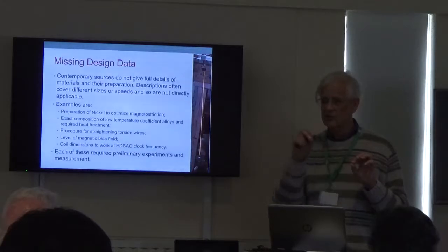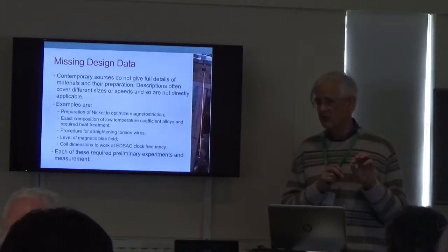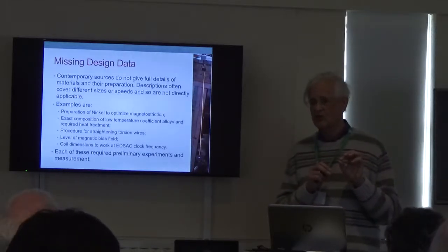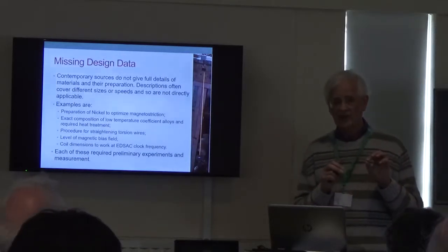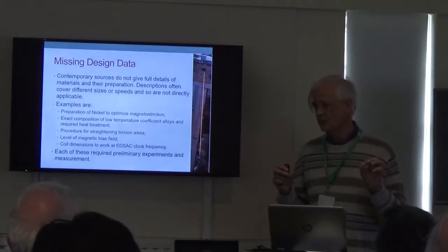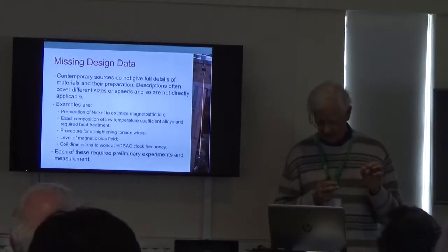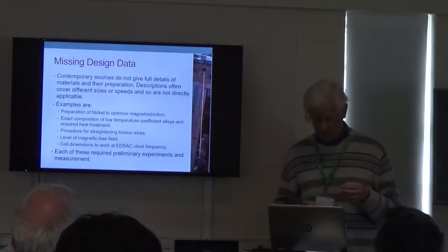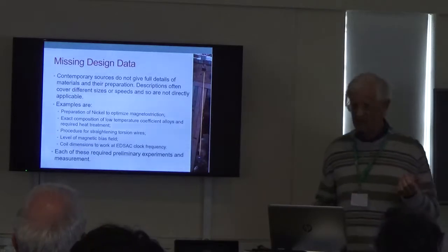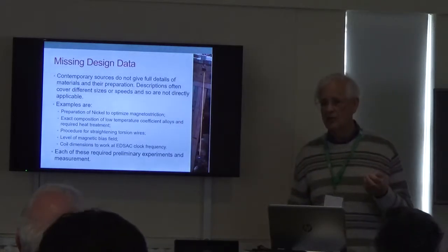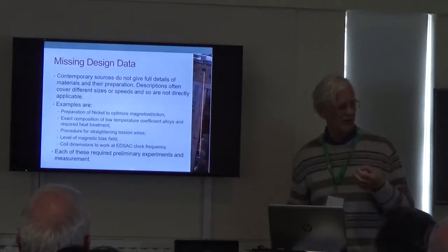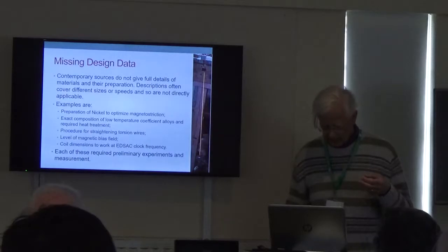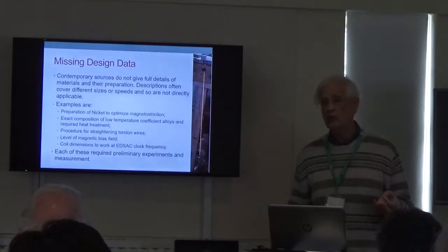Having the sound travel in a spiral also produces a dispersion effect, but they're opposite signs. So if you start with a wire which is straight and then curl it up, the dispersion from the two causes cancels, which is nice. But it means you've got to find out how to straighten a long piece of wire. It's not easy. So we have a procedure for doing that by, again, passing a current down it and blipping the temperature so it just softens, and dropping it again.